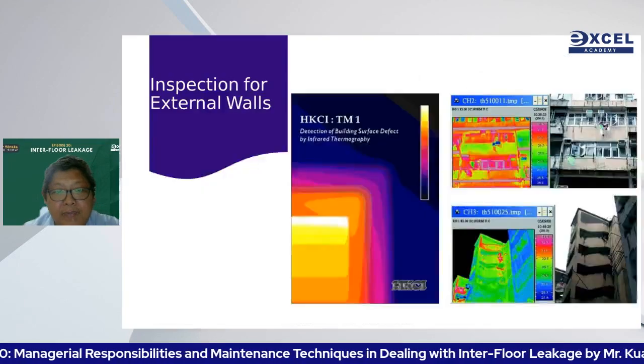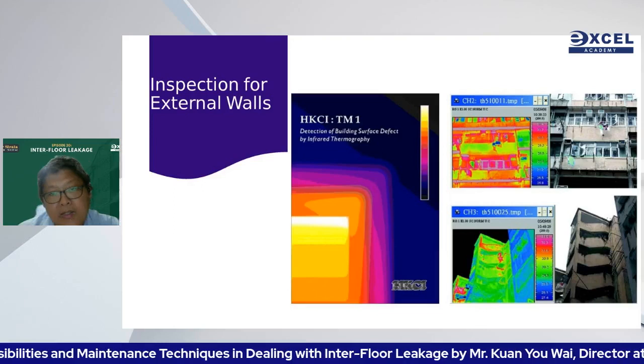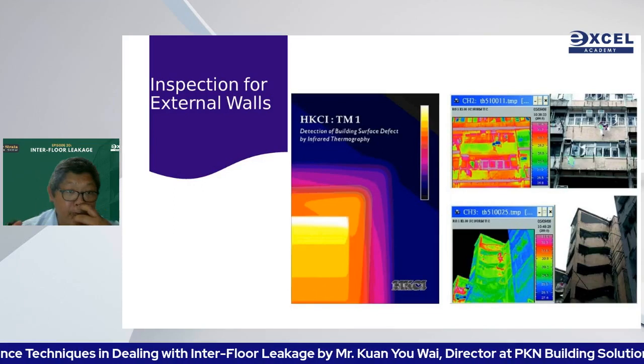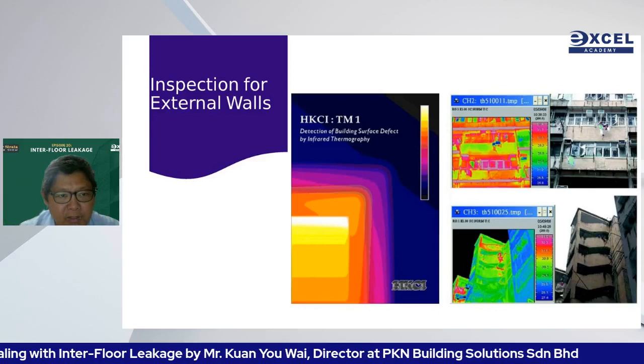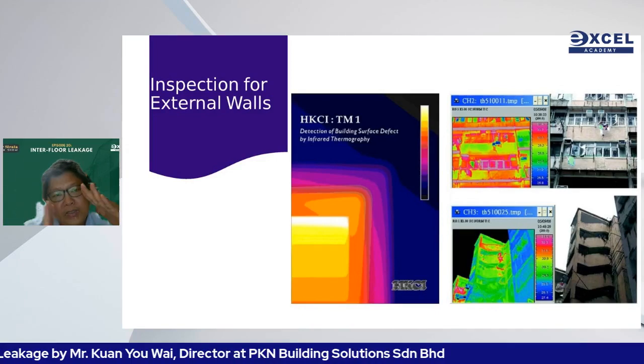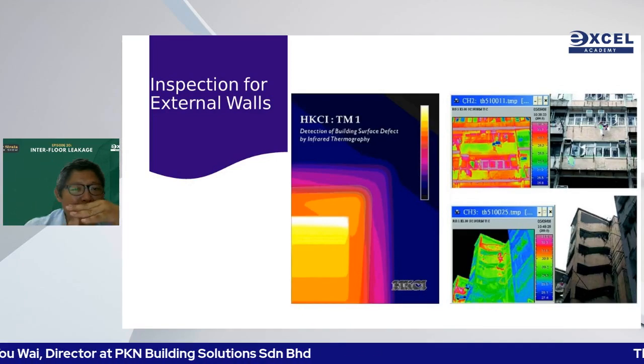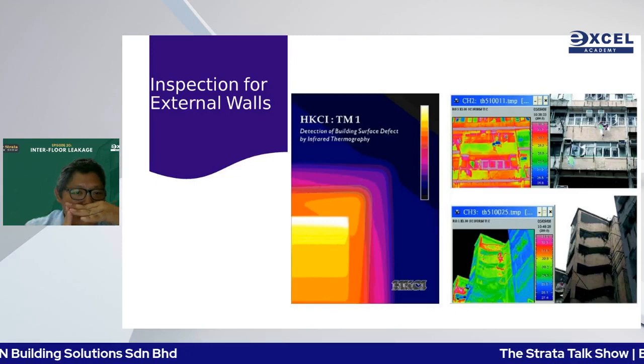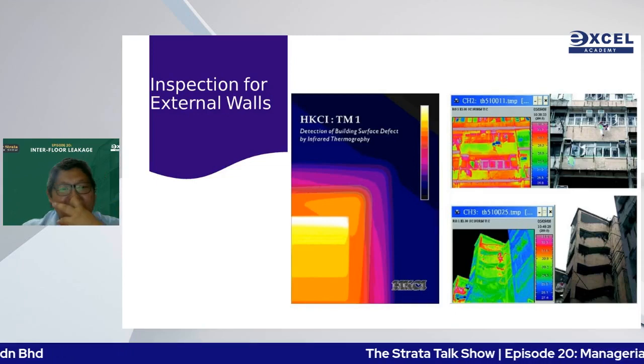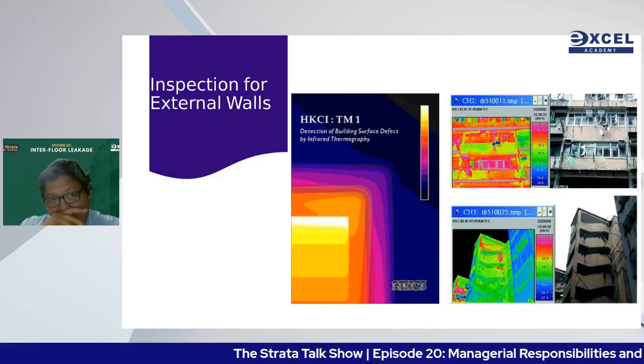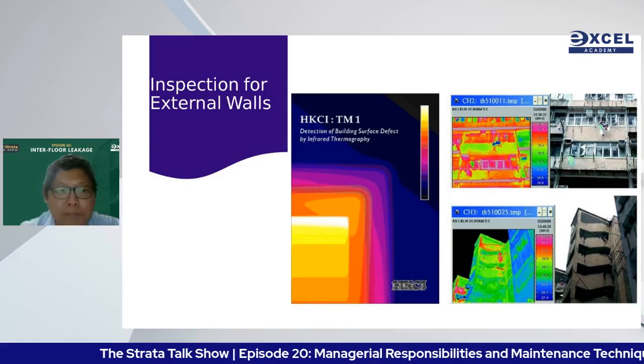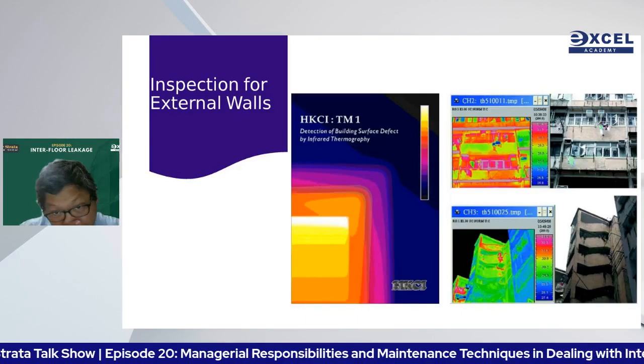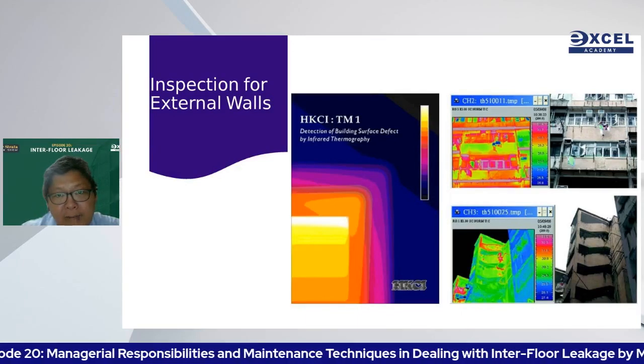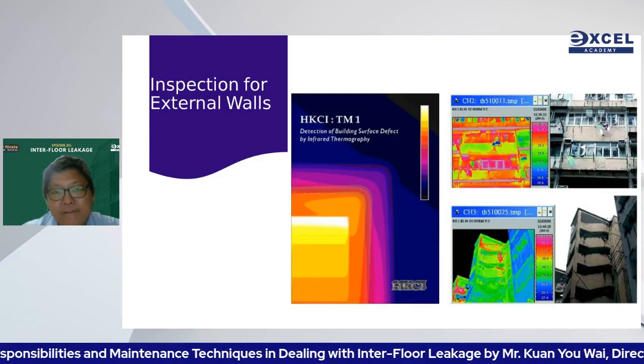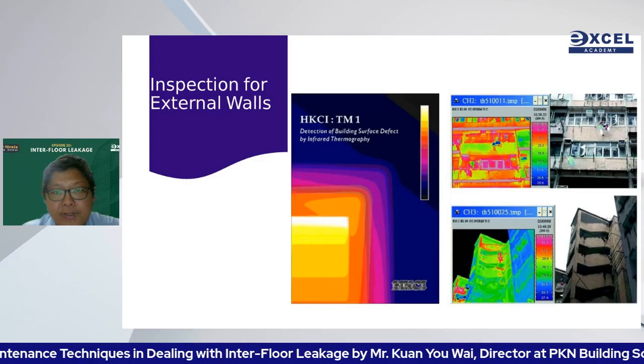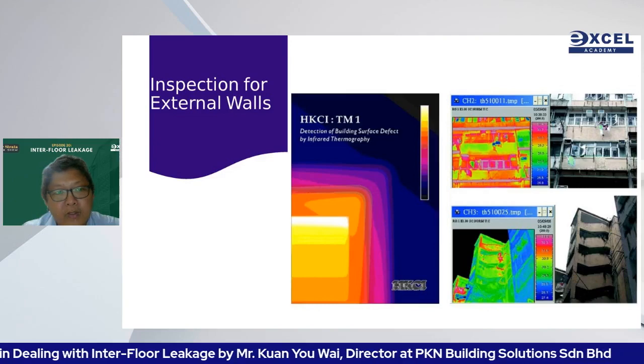Next slide, please. All this is because different building materials have different coefficients of thermal expansion. So when we assemble them in different orientation, when they expand and contract, the wall will crack very badly. So HKCI: TM1 is one of the standards used, adopting the technology of infrared imaging to detect dampness and crack surfaces with infrared. It's very convenient and very efficient and very accurate as well.